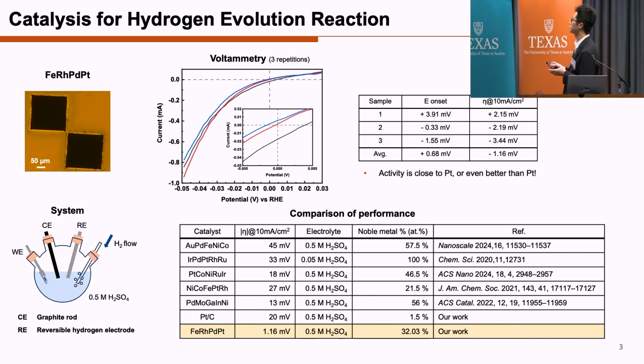Basically, from the average of these 3 trials, we can see that the onset potential is slightly positive, showing that, because we are comparing with the reversible hydrogen electrode, which uses platinum as the catalyst, I can say that the activity is close to platinum or even better than platinum. And I'm also showing the overpotential value at a certain specific current density, and we can see the value is pretty low. I'm comparing this value to other similar works that also focus on high entropy alloys in the acidic hydrogen evolution reaction.